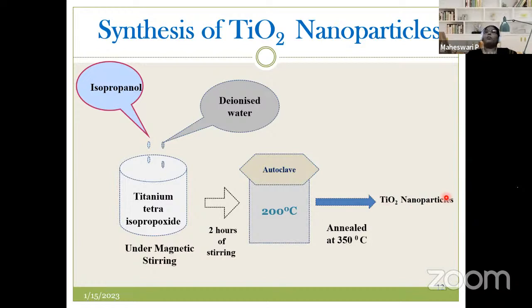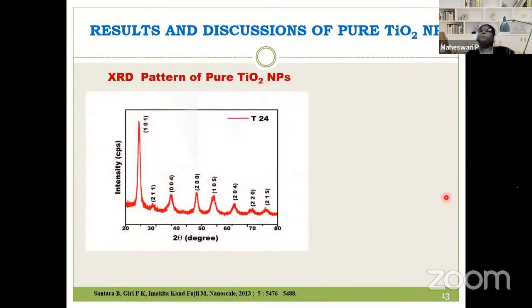Now this is what we have done experimentally, so we need to do some experiments for characterization. This is a confirmation. For that, we went for XRD diffraction, where we got this data, and the plot has been assigned here. We can see clearly, based on the XRD pattern, there are sharp peaks. These sharp peaks clearly indicate that they are highly crystalline in nature. And among these planes, we can see the 101 plane, which obviously comes under anatase.